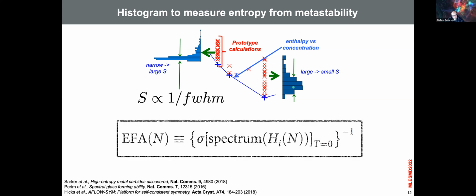All right. So for us, entropic forming ability, you get the spectrum of the excited states of the enthalpy at 0 temperature, and then you get the variance. It's very simple, right? Big variance is going to have low entropy. Small variance is going to have high entropy. So that's why you're going to get -1 here. That's very simple, right?